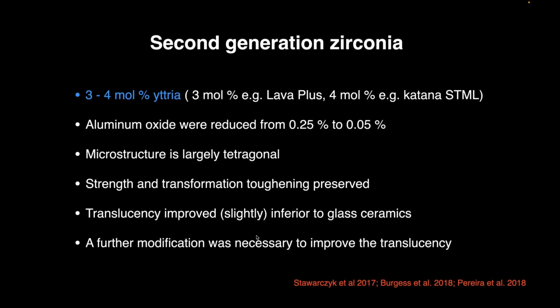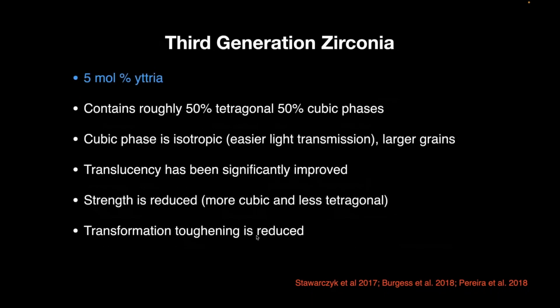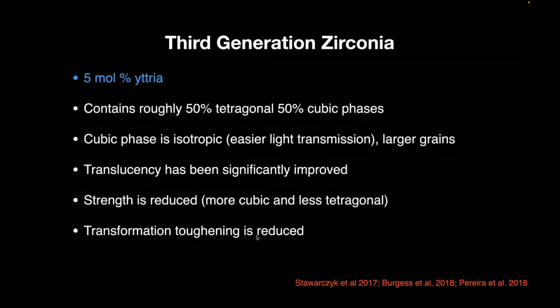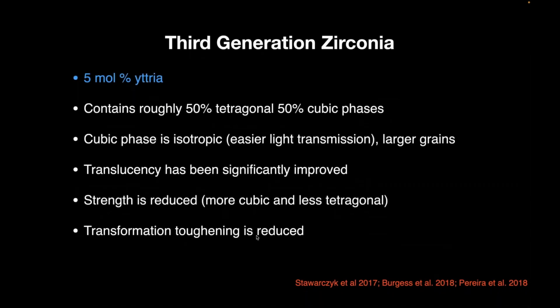A further modification was necessary to improve the translucency, and here is where the 5Y mole percent yttria zirconia was introduced. This one contains roughly 50% tetragonal and 50% cubic. The cubic phase is isotropic, has the same shape in all directions, and allows the light to pass easily, and it provided the material the translucency that is needed. So the translucency has been significantly improved.